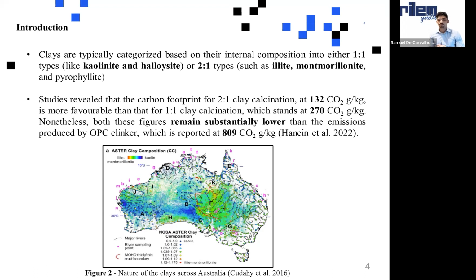LPC and LC3 concrete. Some studies on LC3 concrete have revealed that the carbon footprint for 2:1 and also 1:1 clay is between 132 CO2 grams per kilo and 270 CO2 grams per kilo, which is much less than the emissions produced by the normal OPC clinker, which is around 809 CO2 grams per kilo.